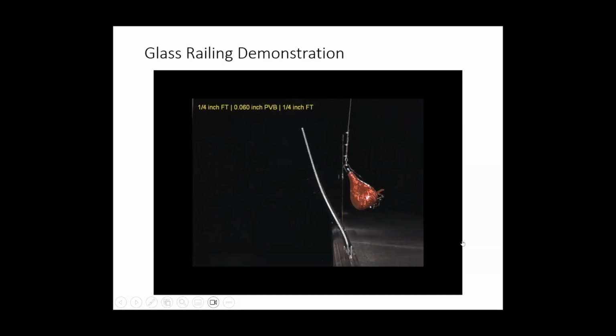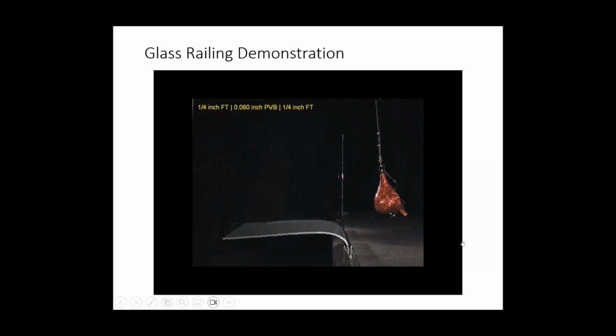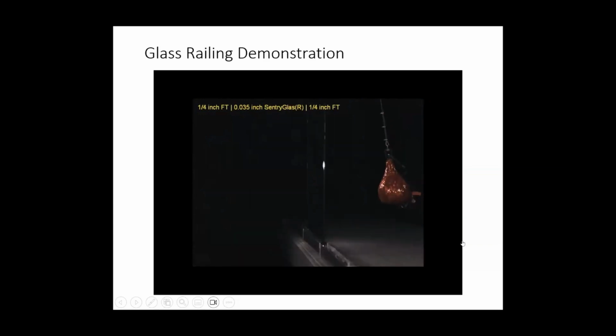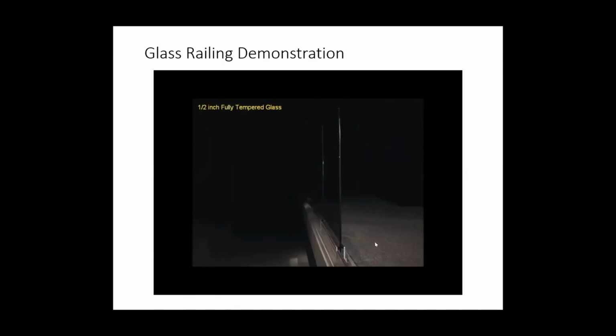Here's PVB. So PVB, see, almost no glass falls onto the sidewalk, but the glass falls over like a wet noodle. So if there's a child up there, they could easily fall off. Here's the ionoplast. See, the glass does break, it deflects, but then it just pops up in place. So it can be a barrier until you get the glass replaced.